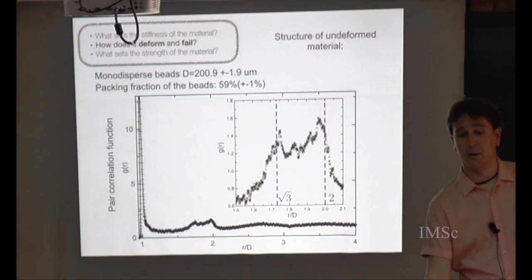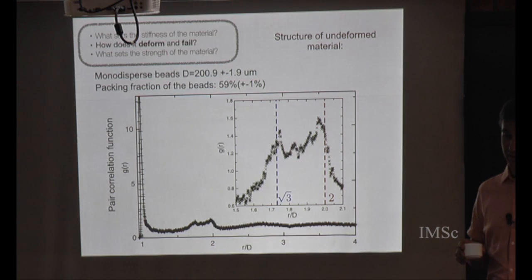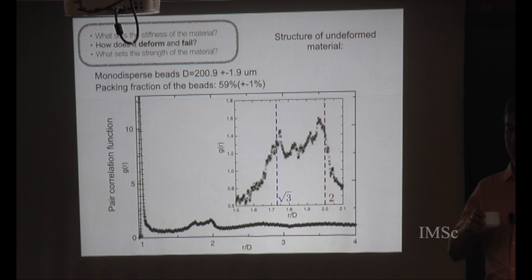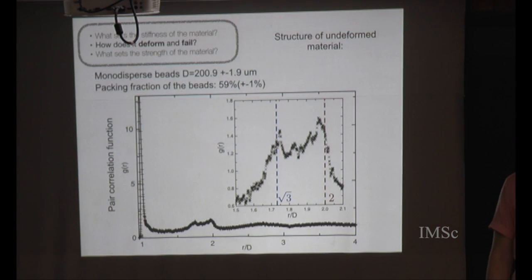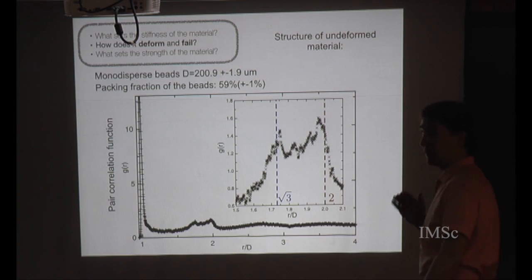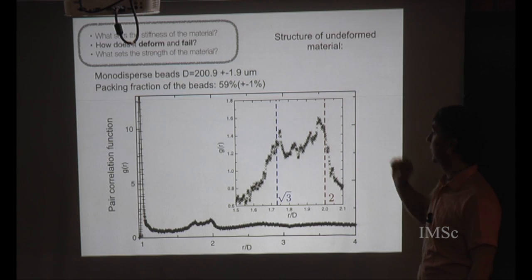So that's effectively irrelevant. So there is a time scale for the scan. It's a few hours, but we tried a few variations on that. We can see everything clearly. There's no blurring, and we can see clean positions of everything. And it would blur if it moved by more than a few microns. The voxel resolution here is about a micron or two. So in order to do this carefully, we also need monodispersed materials and everything. So these are very controlled experiments.